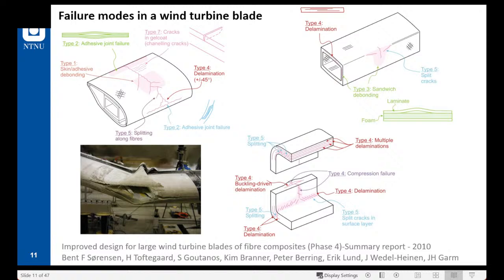Now let's go back to how a wind turbine blade fails. As you can see from these sketches, we can have many different failures because the structure is complicated and we have different types of loads. The most important thing one should realize is that once we have a damage, this may not be critical, but this non-critical damage can trigger another damage, which may be the one that will trigger failure.